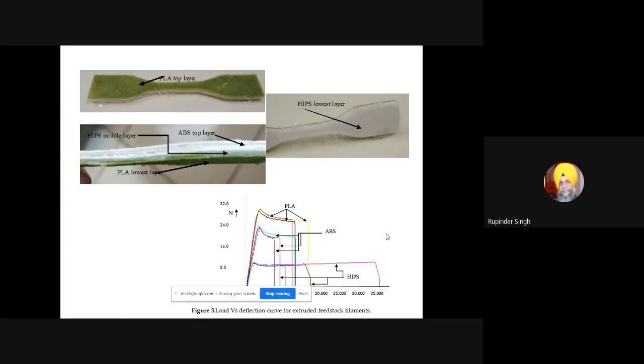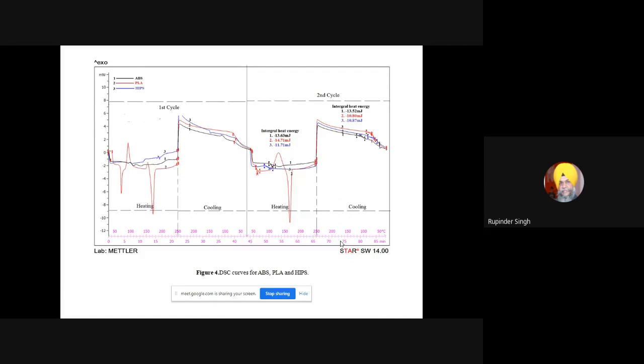Now you can see over here, this is a typical stress strain curve that we developed with a single material. So this is for PLA, then for ABS, then for HIPS, and you can see the area under the curve is basically giving me the modulus of toughness, which is basically responsible for the impact strength of that particular material.